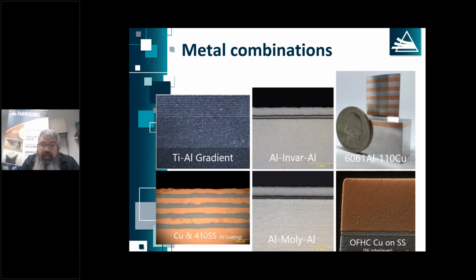You can think of a gradient of CTEs. We can't show many of those because they're proprietary, but the idea is typically to go from the CTE of silicon to the CTE of a heat exchanger, whether that be aluminum or copper. And so you intersperse layers of, say, Invar or moly that have a close CTE to silicon, and then you gradually change to more and more by volume of that aluminum or copper. So there's a wide array of materials that can be engineered by 3D printing to get the exact properties exactly where you need them. We've done variations in modulus, variations in CTE, variations in thermal conductivity, all within the same part.